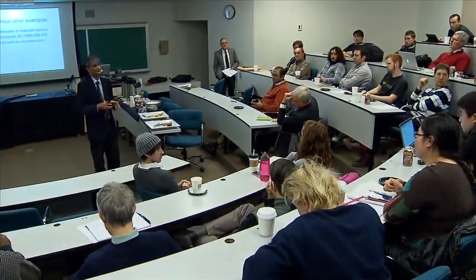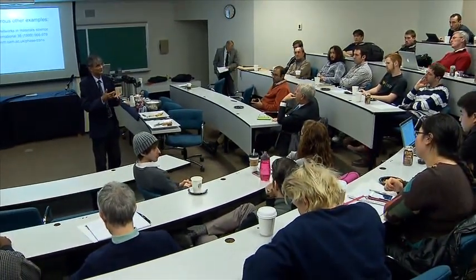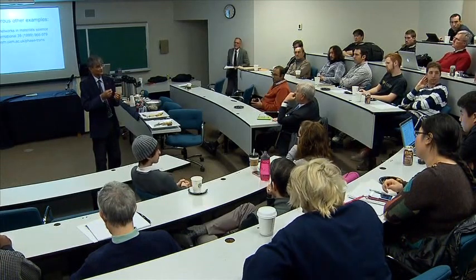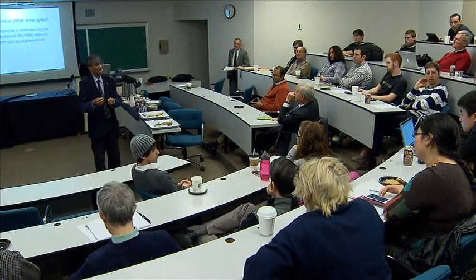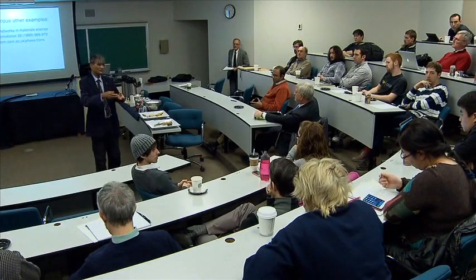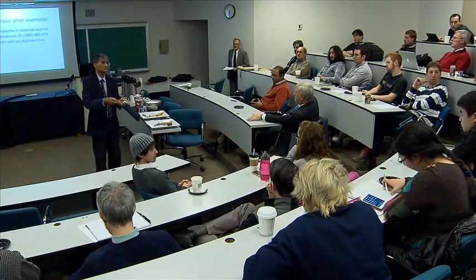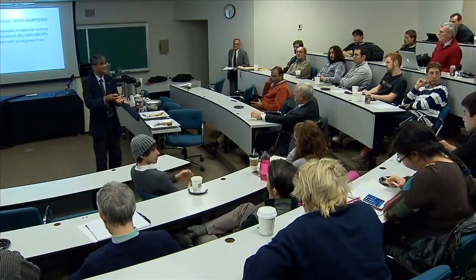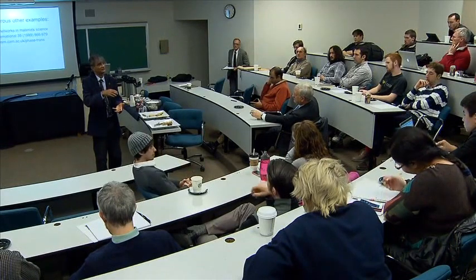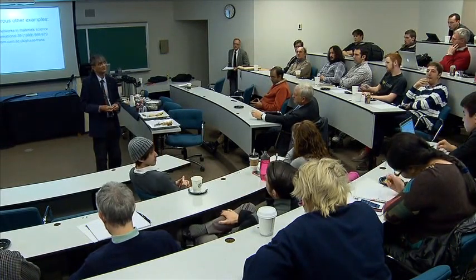Other questions? Yes. I think I missed some part of your presentation. Is that remaining austenite and bainite doubly responsible for the TRIP mechanism? Yes, absolutely. It's that small amount of austenite, the 15%, which trips and causes work hardening. It trips in regions where you have a stress concentration of some sort, and therefore it hardens that region, and so you don't get the instability too early in the process.